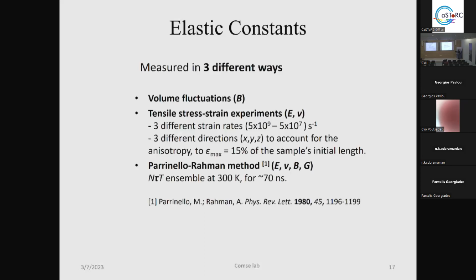And the results for these three different rates are the same? No, we have some variations, but we agreed that in the third, which does not appear here, the 5 times 10 in the order of 8 is the best rate. The best in what terms? In terms of the time of the calculation, it's not 3 months for each calculation. Which one is closer to, for example, Parrinello or Rahman? Which strain rate? The 10 orders of 8. Yes, it's equilibrium.